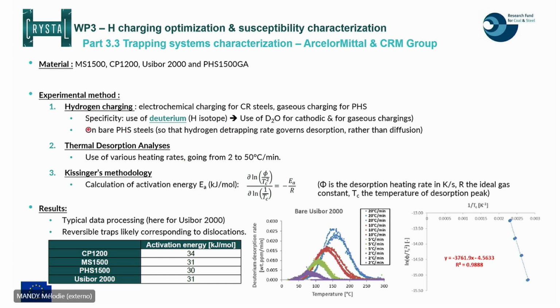This was also performed on bare steels in both cases, not only for PHS 1500, because in the case of the presence of a coating, this will induce a step of diffusion that will be slower and that will have an impact on the results. After that, we performed the thermal desorption analysis with various heating rates, and we applied the Kissinger methodology.